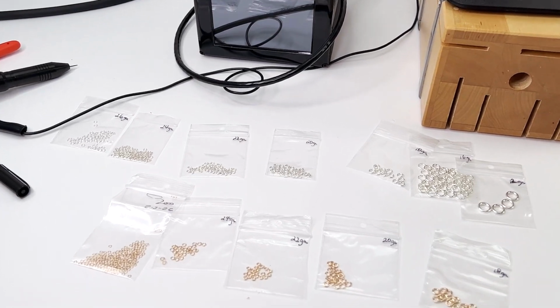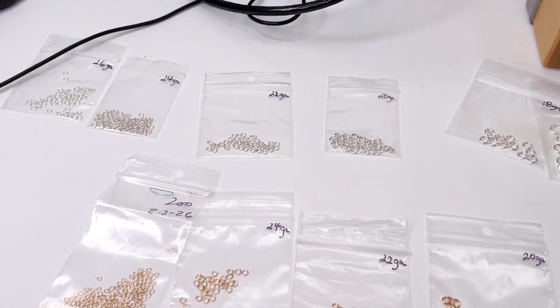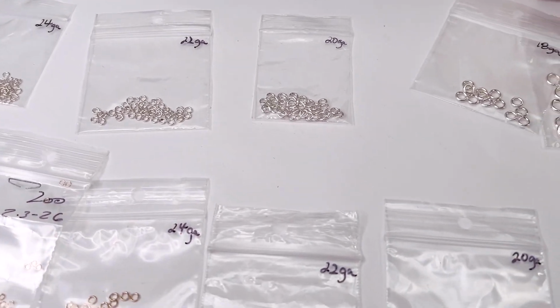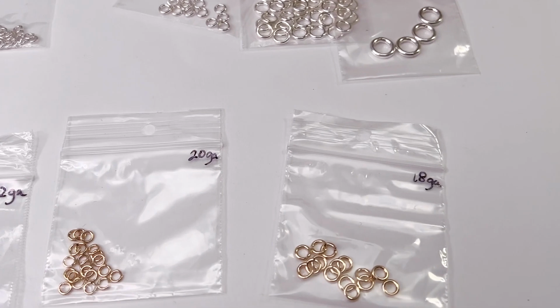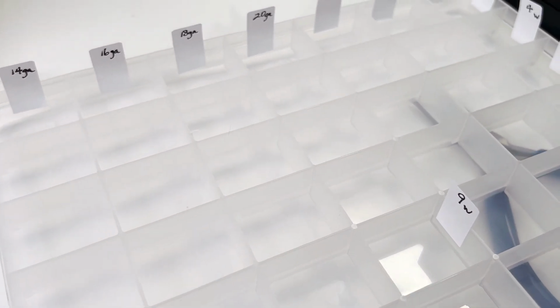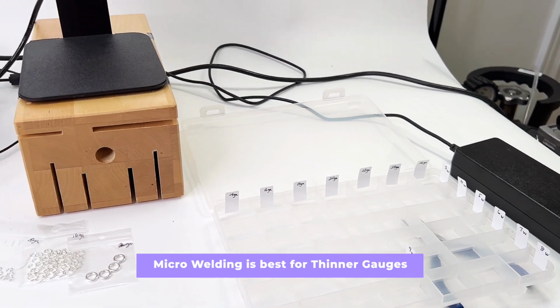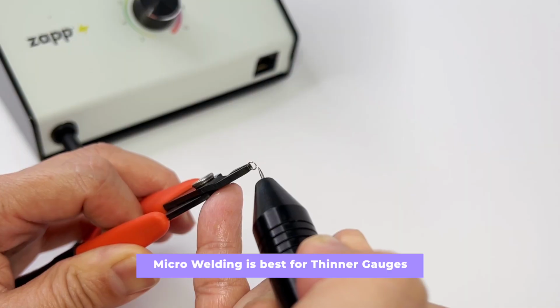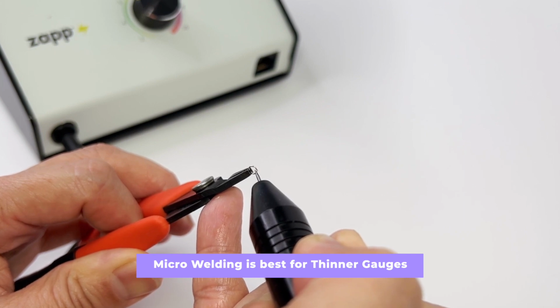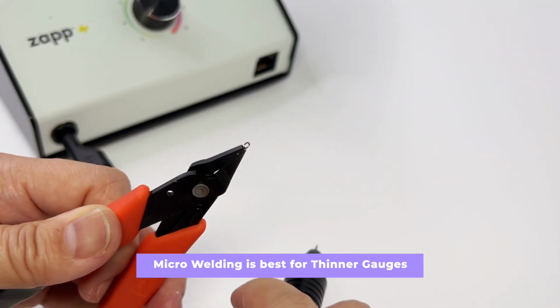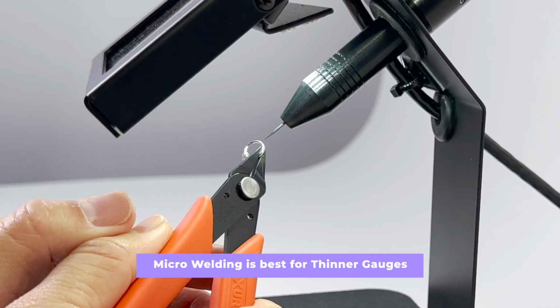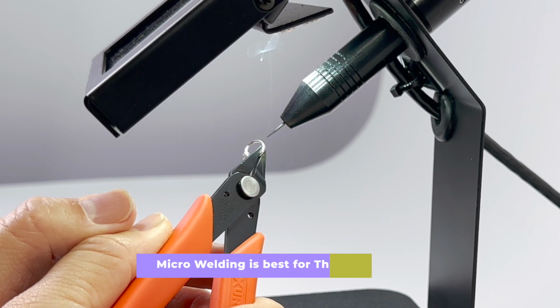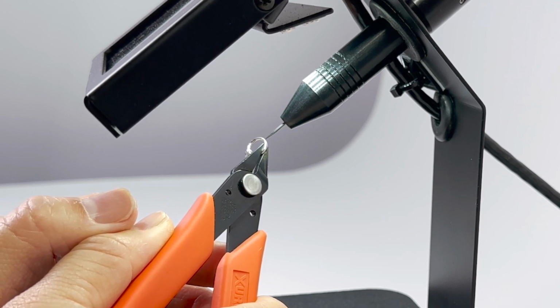Moving on to thickness. When discussing thickness, I will be limiting our discussion to gauges that are most popular for permanent jewelry, as well as some thicker sizes that might be used for rings and thin bangles. Micro welding is best suited for thinner gauge items because the penetration with arc pulse welding is limited in depth and thicker pieces are better soldered. For now, I will experiment on thicknesses between 26 gauge, which is about 0.4 millimeters, and up to 12 gauge, which is 2 millimeters. I will get some wire and try out other thicknesses to fill out my chart another time.